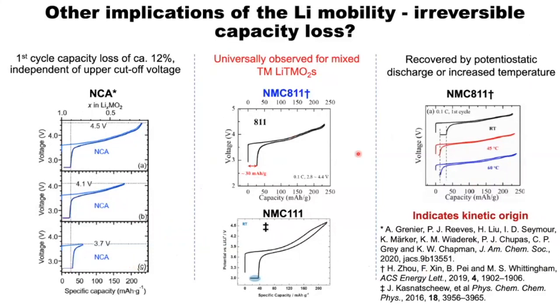I want to look at this issue of the first irreversible capacity loss on the first cycle. And so this irreversible capacity loss seems to be quite consistent amongst a whole variety of different nickel-rich materials, whether it's 811, or NCAs, and work by Karina's group in Stony Brook and also Stan Whittingham's has shown that this is largely kinetic in origin. So if you, for example, go from room temperature to higher temperature, and this is Stan's work, you can actually reduce the first capacity loss.